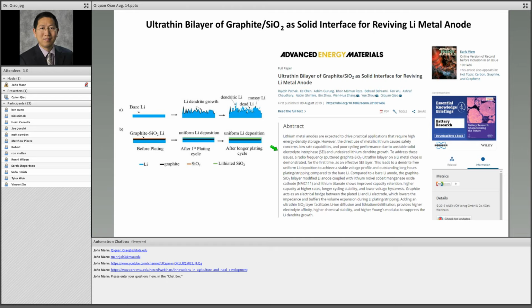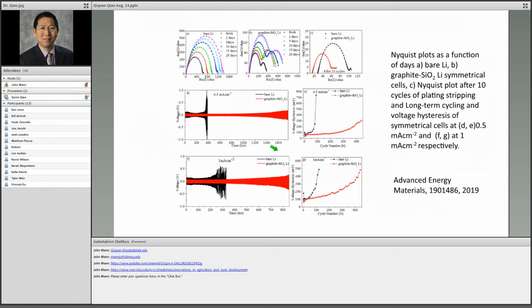Another project has the same purpose. We try to protect or passivate the surface of lithium metal. What we use is actually graphite and silicon dioxide instead of lithium nitride. This graphite silicon dioxide was made by sputtering, and the work has been published in Advanced Energy Materials. With this graphite and silicon dioxide protection, you can see the battery can run about 2,000 cycles, compared to without it, where the battery will die at around 400 or 300.